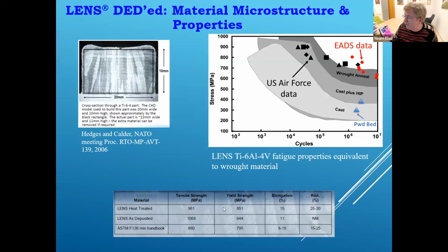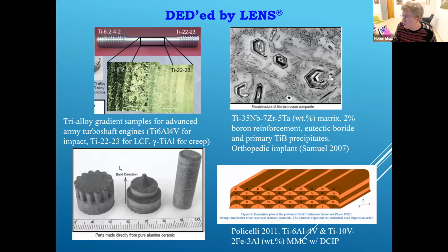And at the bottom, you can see for titanium alloy that typically the as-received material with DED can get mechanical properties that already satisfy the ASTM or ISO standards in terms of static strength and elongation. Some further examples from a thesis already from 2007. This is titanium-based alloys with titanium boride precipitates. Look how nice the interface between the precipitates and the matrix is.